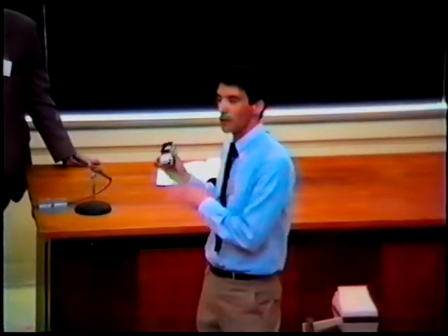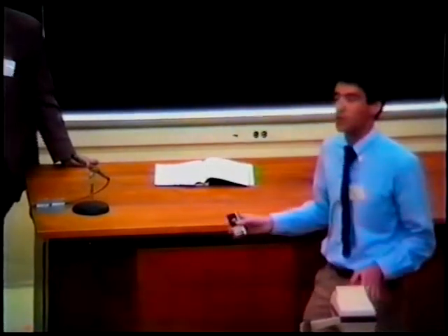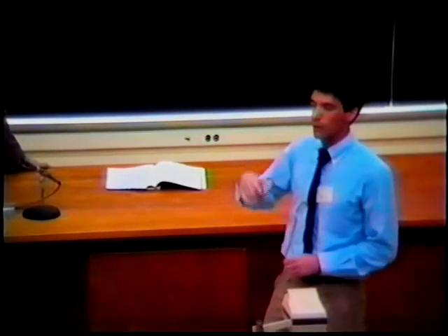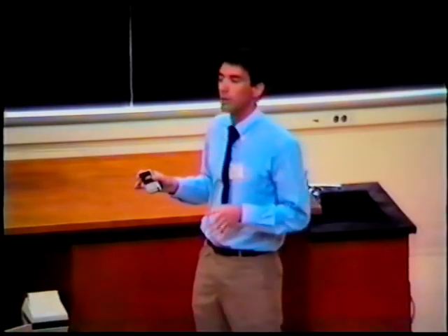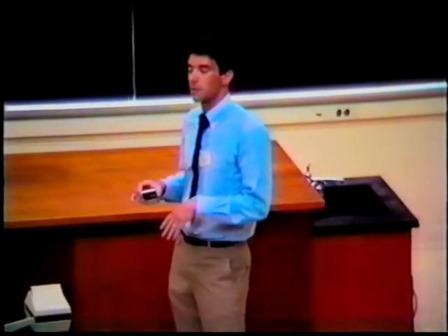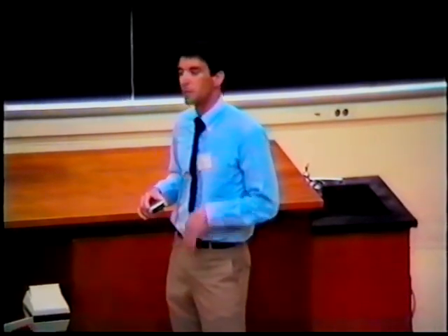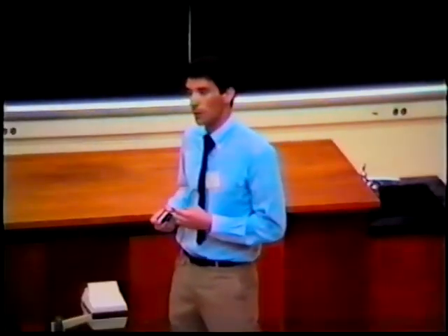That's right. The model, as it stands, does not introduce that. We just assume rigid particles. But we hope that it can be used via the perturbation theory approach that's often used in liquid state theory. Once you have the thermodynamic properties of a hard sphere system, it's easy using perturbation theory to tack on the effects of interactions between particles. So the work definitely needs extending in that respect.